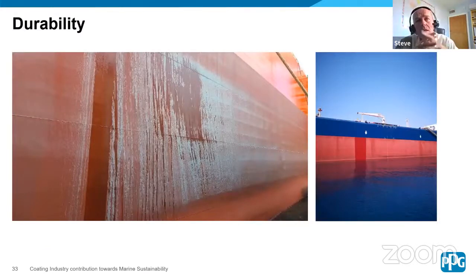Now, I mentioned the chemists tap into the very reactive nature of copper, but it's also its Achilles heel. And this is what I mean. A picture on the right showing you how under certain climatic conditions, copper can recrystallize on the surface, forming copper salts. This copper patina will eventually wash off, but it just shows you the nature of the material. And in the picture on the right, where you can see a test patch of copper-free material in the middle, this is only 6 months in service, and yet this red-brown antifouling is already turning quite pink, whereas this red-brown antifouling is still red-brown, and handsomely so, it has to be said.